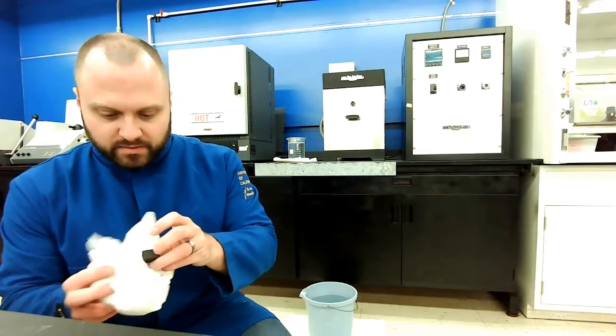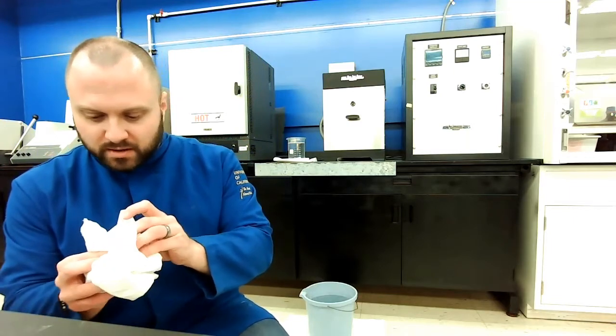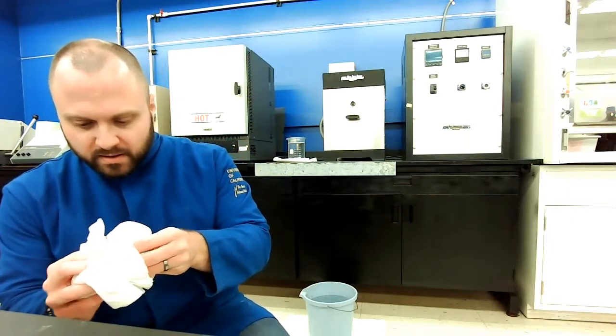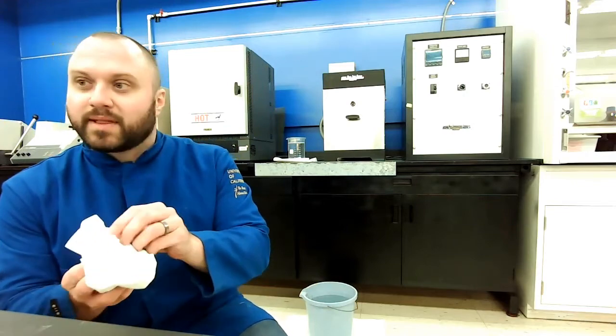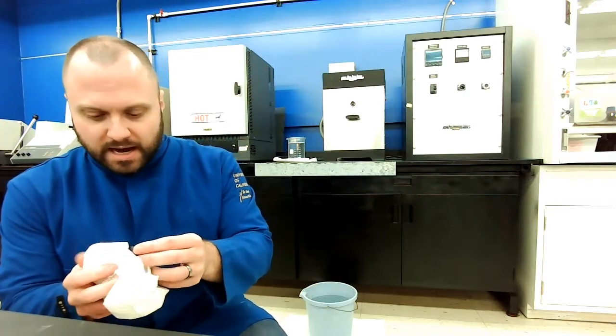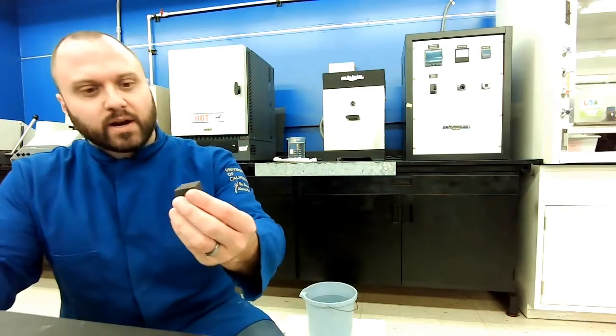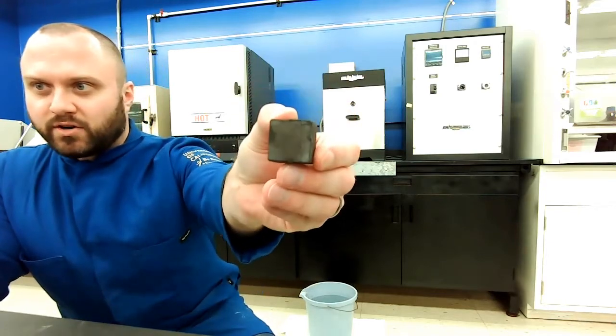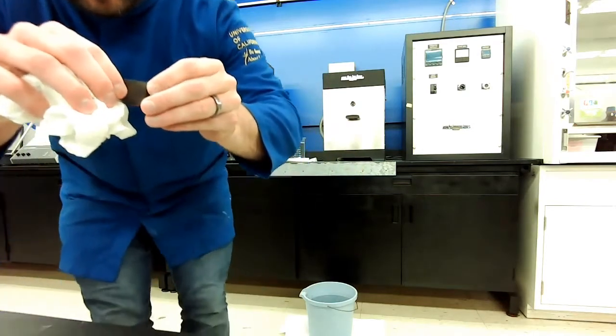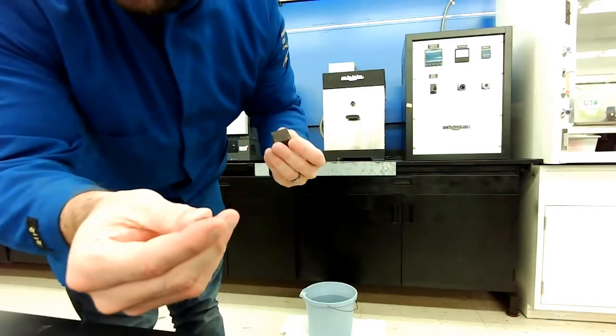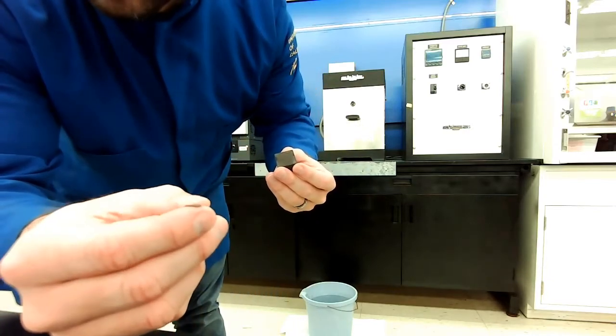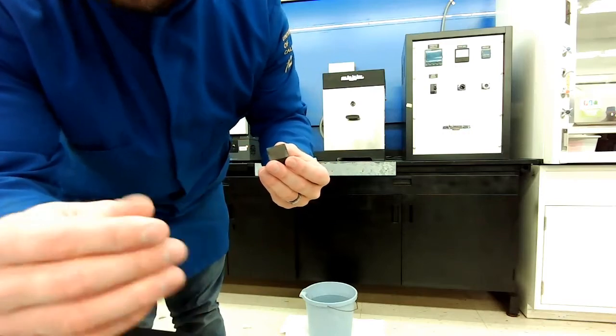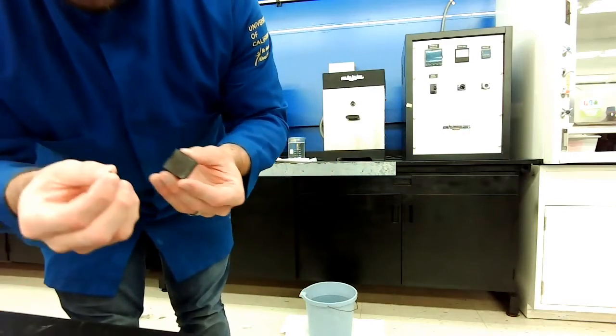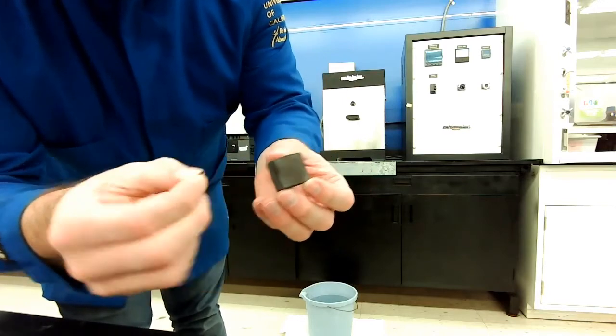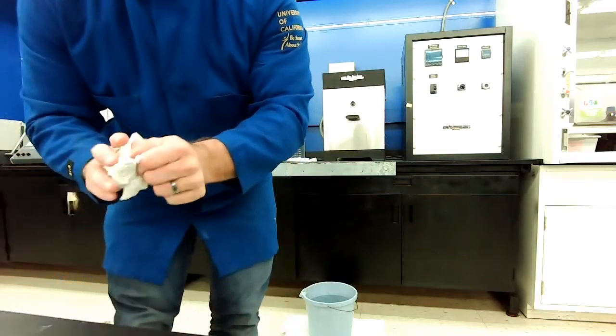Take this out, dry it off. What's kind of cool is a lot of the outer shell, so some of that oxide that formed at high temperature, actually broke off when I quenched it. So you can see it's still pretty dirty, but find a piece that just flaked off. So a piece of that oxide flaked right off the surface. Okay. Let's pull another one off the surface too. So we have 2 of our 3 samples.